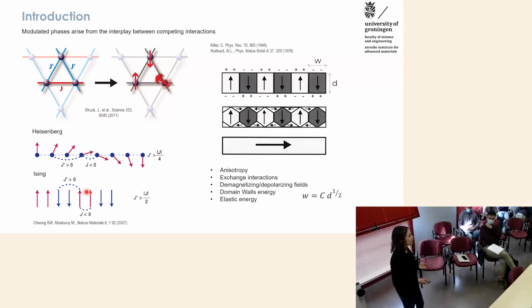But modulated phase can also arise at a larger scale, for example, between domains, when there is a formation of domains in films. And this again arises from the competition of different forces. We always have some anisotropy that can be the anisotropy of the magnetic material or the shape anisotropy induced by the growth on the thin film. And then there is always the exchange interaction between spins.